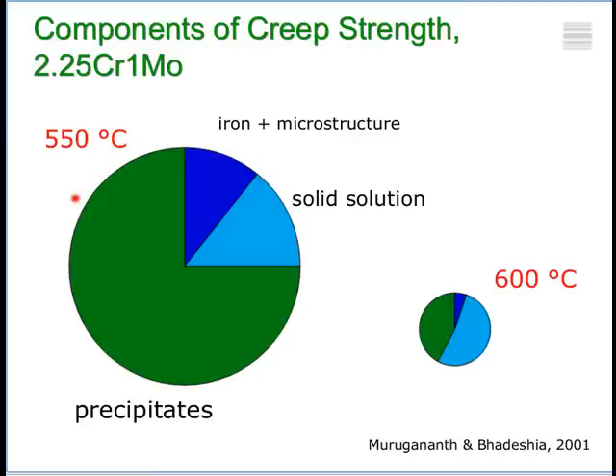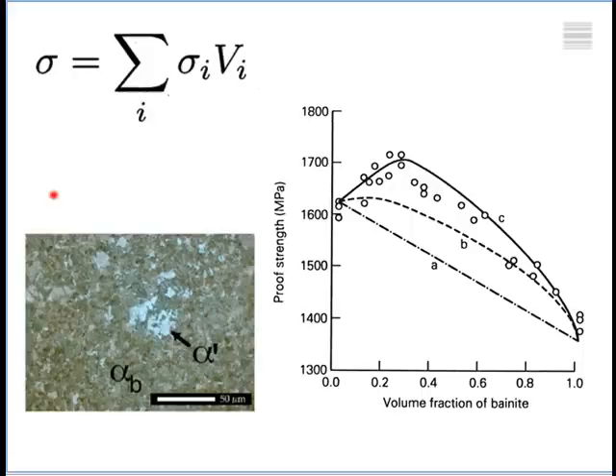Now, of course, so far I've considered essentially single-phase microstructures. That means we have ferrite or we have perlite. If I go to mixtures of microstructures, so here we have a mixture of bainite and martensite, then the simplest thing to do is to add them up by taking the strength of bainite, multiplying by the volume fraction of bainite, adding to it the strength of martensite multiplied by the volume fraction of martensite. So this is called a rule of mixtures. And if I plot how the strength should vary as a function of the volume fraction of bainite, I would get this straight line here.